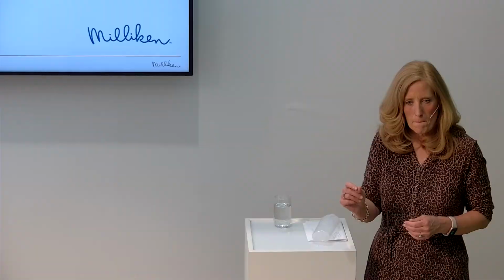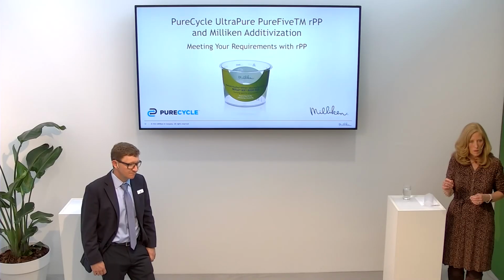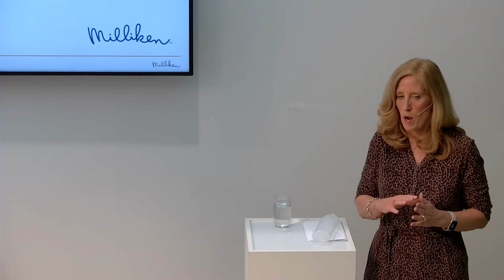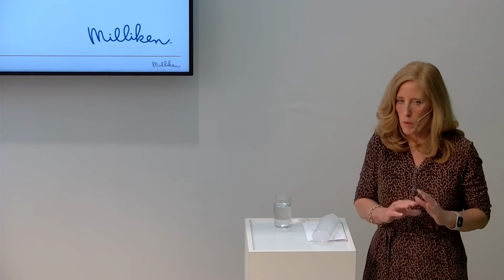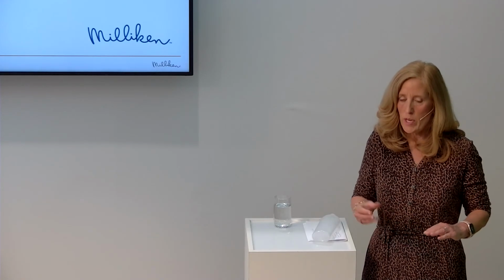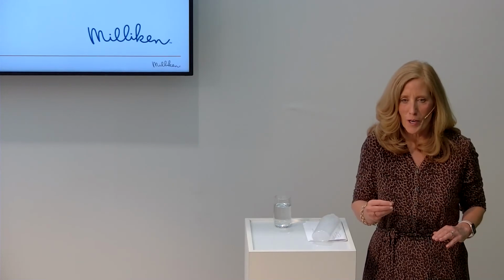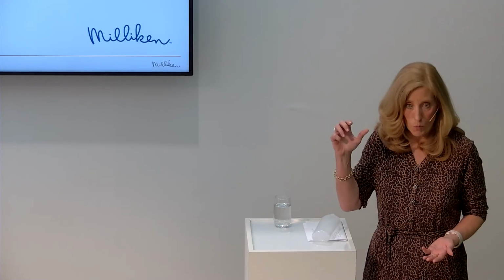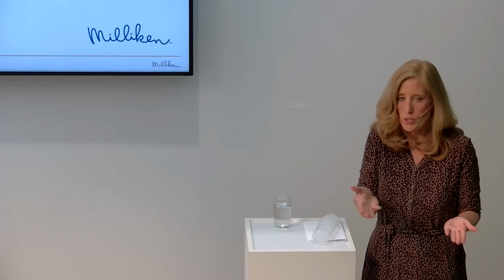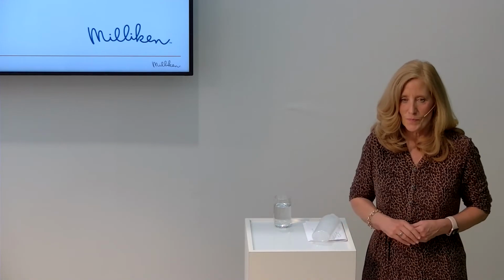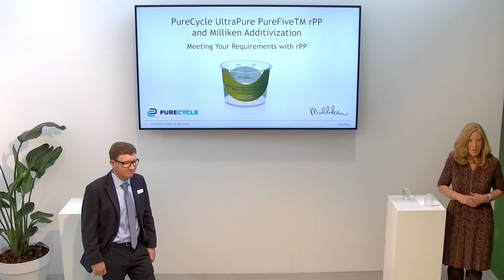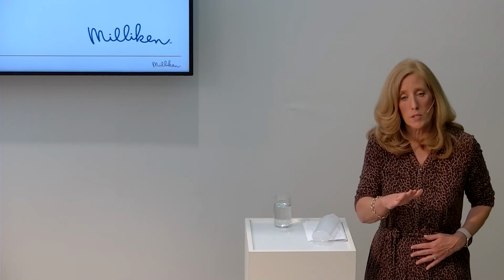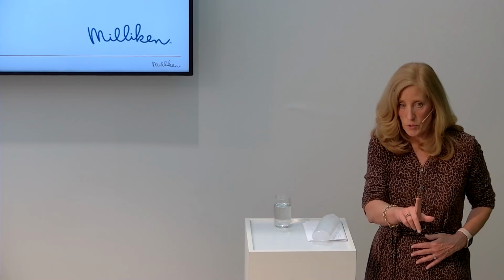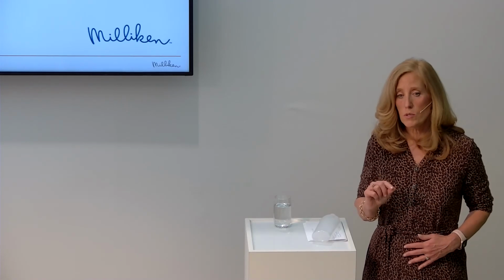So you're basically not substantially shortening the chain length of the polypropylene as such. We're not affecting the molecular structure of the polypropylene at all. Okay. We dissolve it like salt gets dissolved in water. Evaporate the solvent, water, and you're left with salt again. We don't change the salt. Then I'm probably misled by what people are doing with polyester. Yes, so depolymerization is a different story. This is dissolution, so it's a little different.